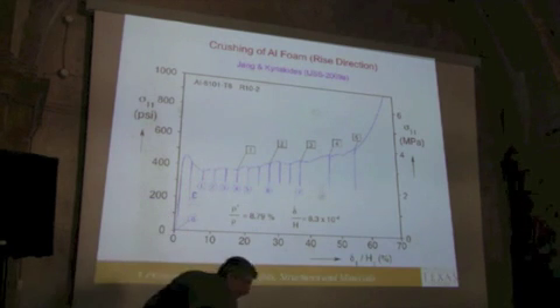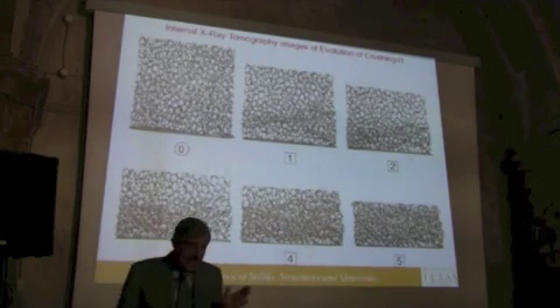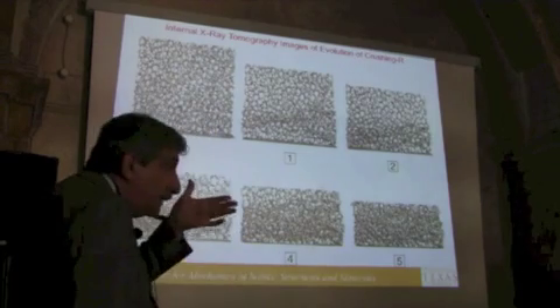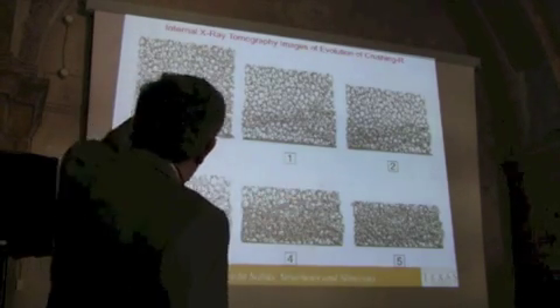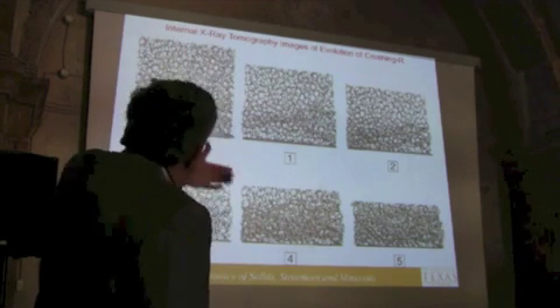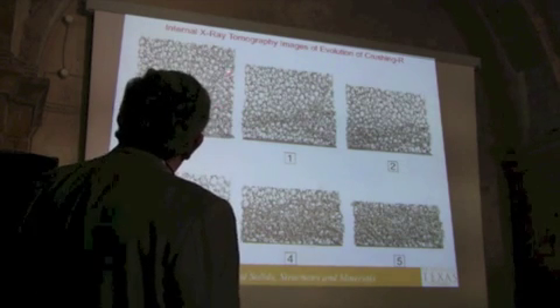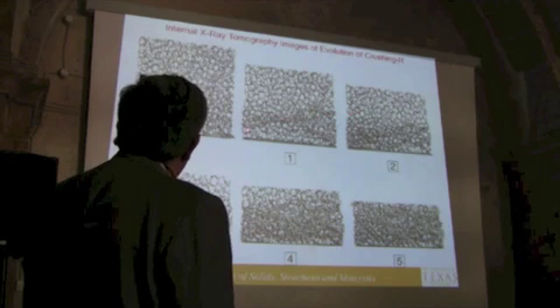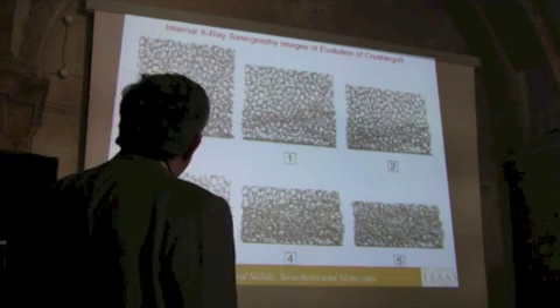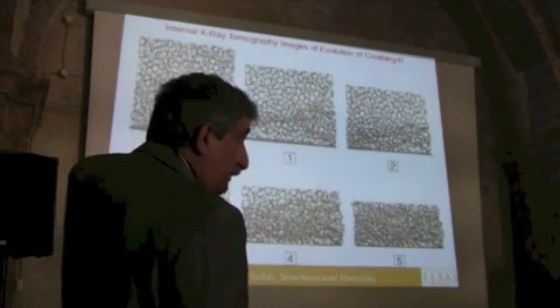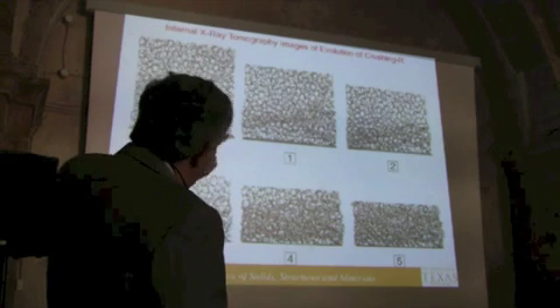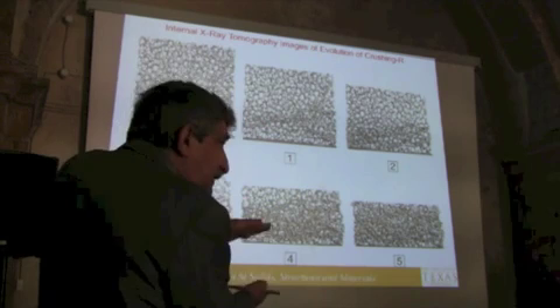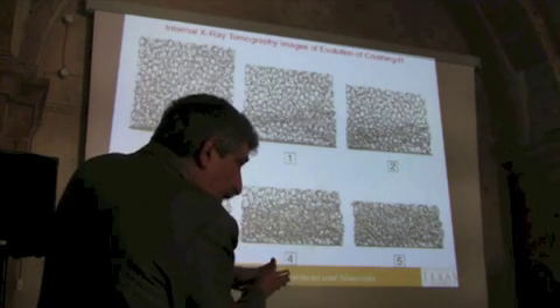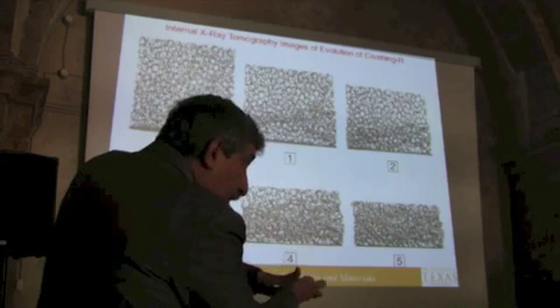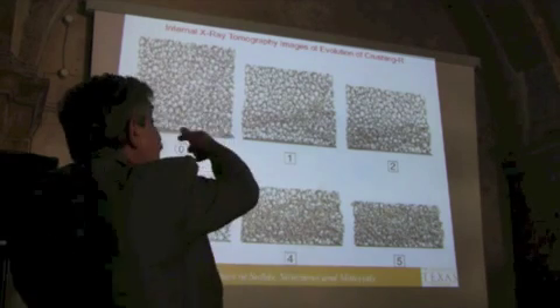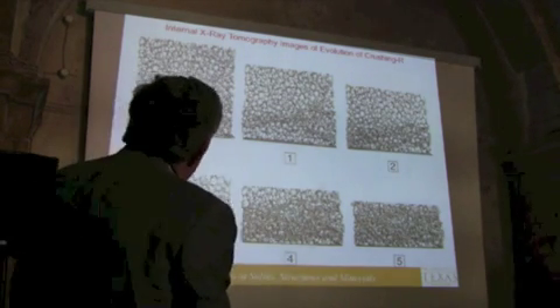But again, you see this general sort of response, and from those scans, the tomography gives you the full field deformation, and we choose a slice through the depth. And this is 50 by 50 millimeters, and you see what happens. It's crushing. It's similar to what we saw earlier more clearly for the 2D case. I have more details, but I don't have them here. The cells locally buckle, crush, the ligaments come into contact, the local crushing stops, and in the meantime the neighborhood gets destabilized, and in that sense it propagates.